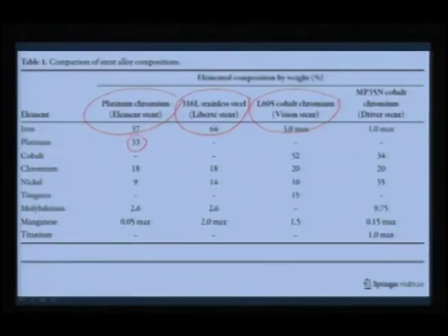coronary artery. So, when you say platinum chromium stent, then you are talking about platinum 33%, chromium 18%, but still you have a larger proportion of iron in this stent. Similarly, when you say stainless steel, the greater proportion here is iron, whereas you still have chromium and nickel involved. So, it does not really go by the nomenclature, but principally the shape memory effect is actually coming from this alloy composition.